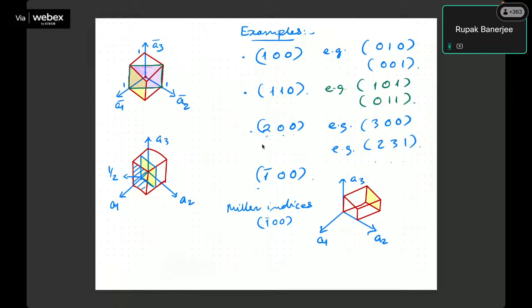Another important thing to note here is that if you look at the 200 plane, right, remember, we are always looking at the intercept, not at the actual. So 200 doesn't necessarily mean, as a lot of students suffer from this misconception, that it might be double. It is actually half, right? So if you define the 100 plane, which is here, if it is 200, it means it is intercepting the a1 axis at half the distance. So this yellow plane is actually midway between the origin and the 100 plane. Okay, it is definitely a higher order, but because we have defined our Miller indices by the reciprocal of the intercepts, it is 2. Similarly, 300, which means it has to be further down, which means 1/3.